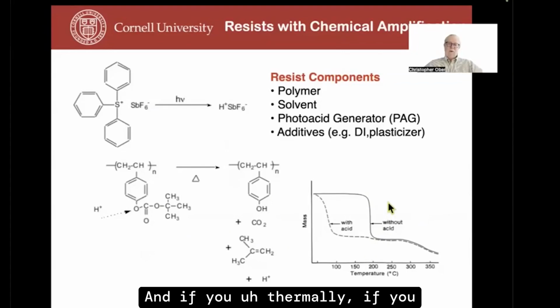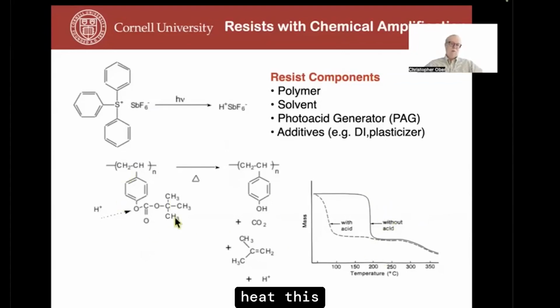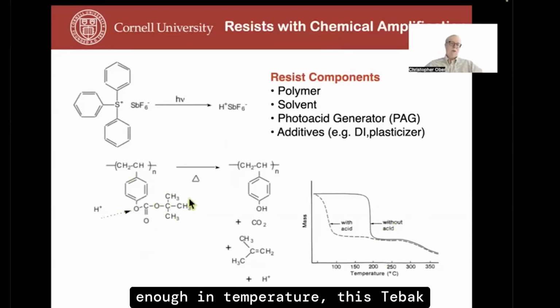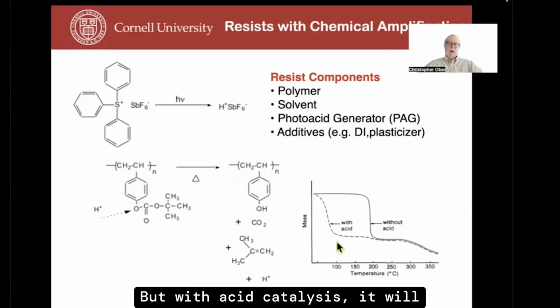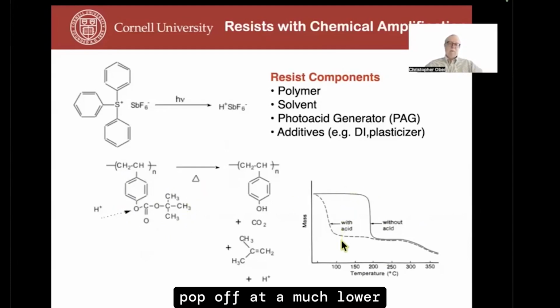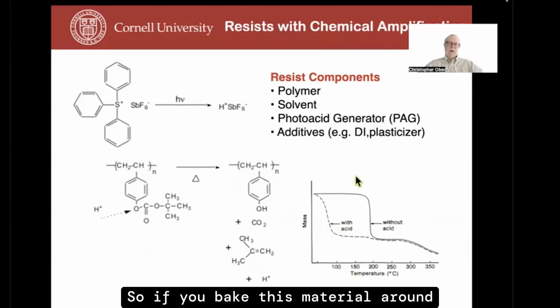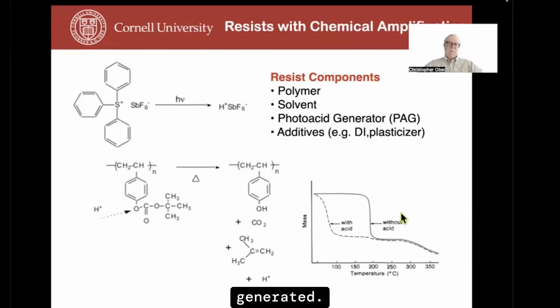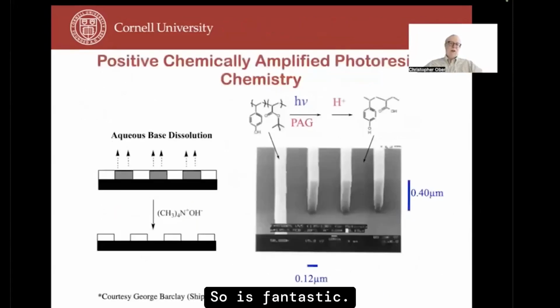And if you heat this particular polymer, if you go high enough in temperature, this T-BOC group will pop off. But with acid catalysis, it will pop off at a much lower temperature. So if you bake this material around 125, 130, 140, 150 degrees C, you can deprotect in the acid-rich region, and you do nothing in the area where acid has not been generated. So this is fantastic. And suddenly the whole world turned to chemically amplified photoresists.